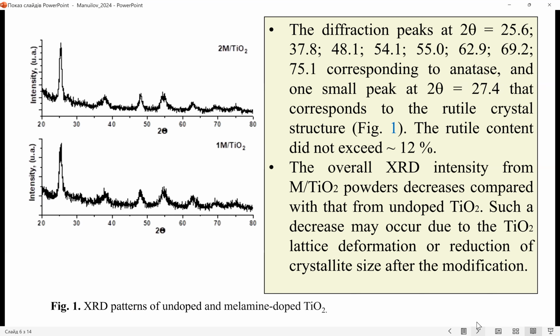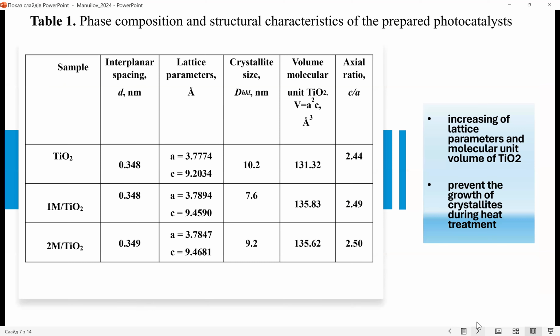The diffraction peaks at 2 theta equals 25.6, 37.8, and so on, correspond to anatase, and one small peak at 2 theta equals 27.4 corresponds to the rutile crystal structure. The rutile content didn't exceed 12%. The overall X-ray diffraction intensity from M TiO2 powders decreased compared with that from undoped titanium dioxide. The decrease may occur also due to the titanium dioxide lattice deformation or reduction of crystallite size after the modification.